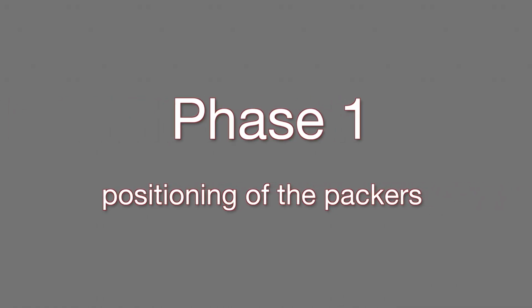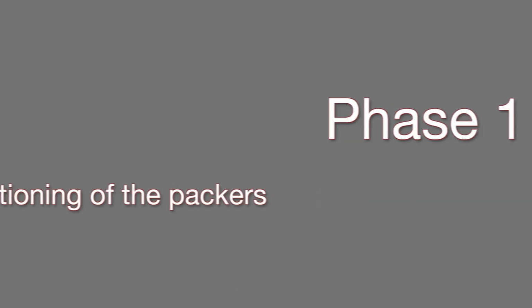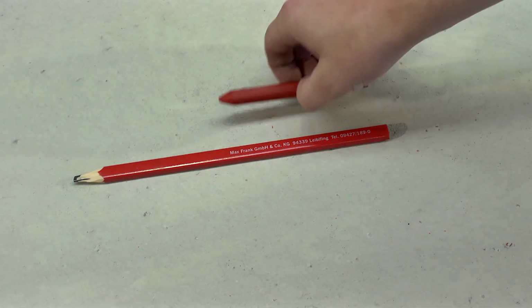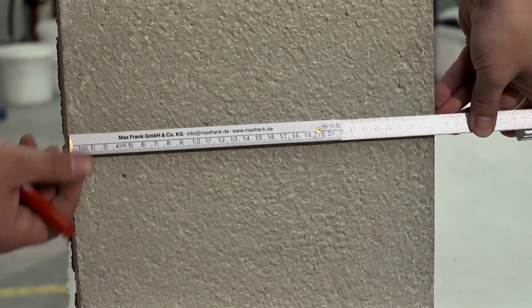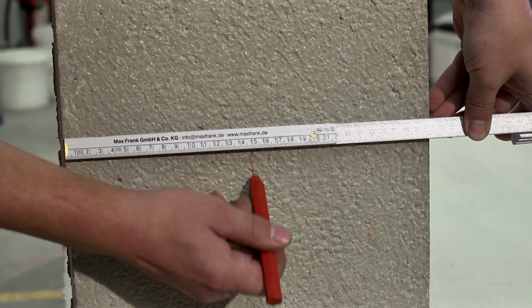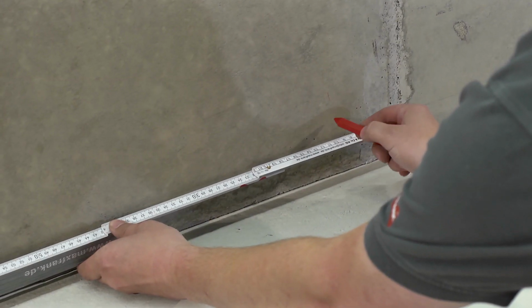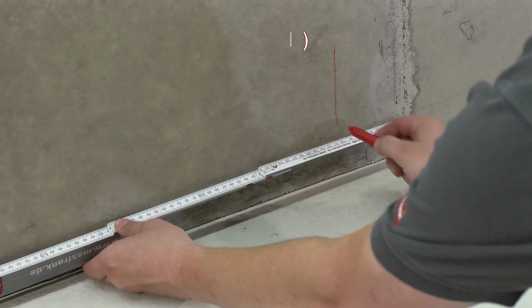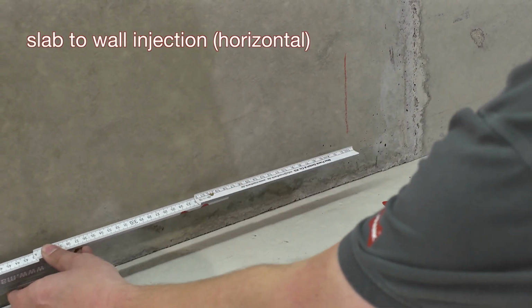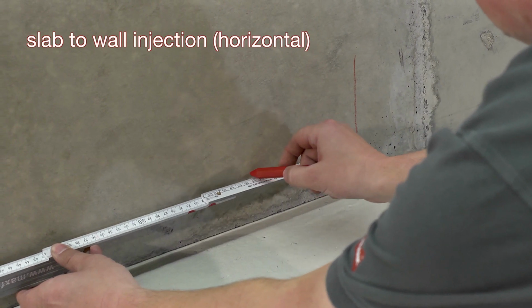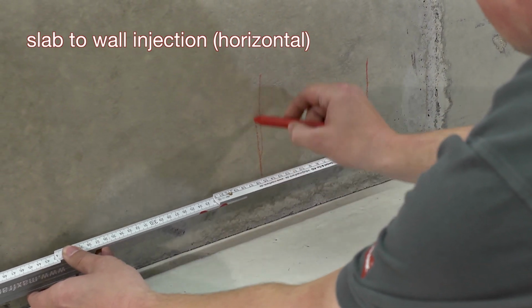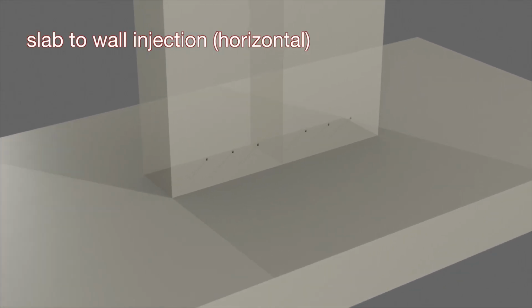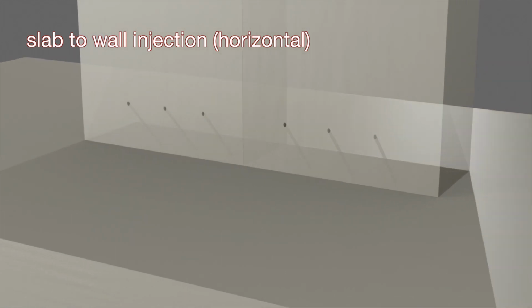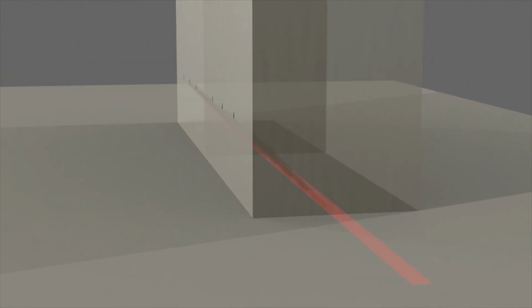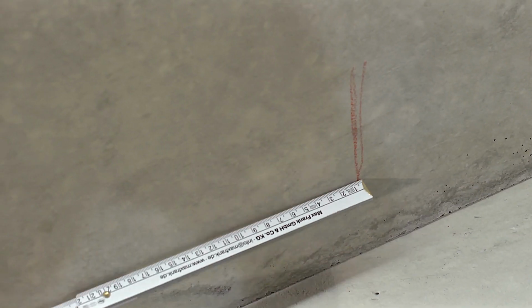Positioning of drill holes and packers. Proper spacing of the drill holes and packers is crucial. Generally, packers are spaced at distances equaling half the cross-section thickness. In our example, 150 millimeters on center. First, a drill template is denoted on the surface in such a fashion that drilling at an angle of approximately 45 degrees will cut across the crack plane at midpoint.